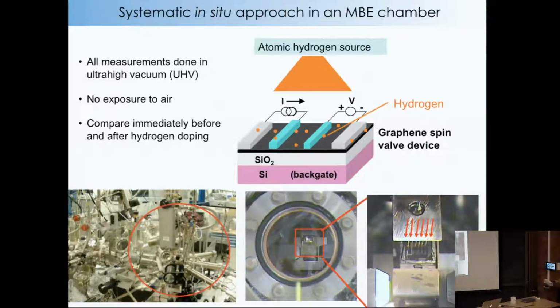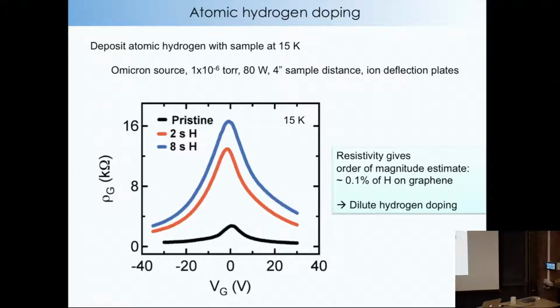So the idea here is we'll make a spin valve, so we'll measure the spin transport, and we'll put on hydrogen from an atomic hydrogen source. And then we just compare before and after, and we don't take the sample out. In fact, we cool it down to about 10 Kelvin or so, put this stuff down, and measure it right away. So it's probably the best that we can do, or the best we can imagine doing, all in situ. First we look at the resistivity as a function of gate voltage, and this is your Dirac point.